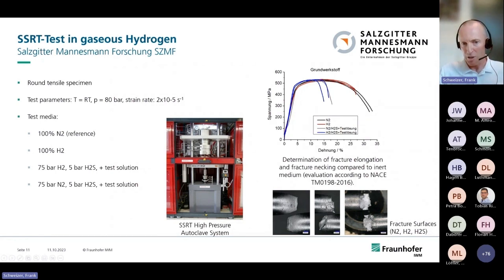So you have a tensile machine, what you see here, and you have an autoclave system where you can have high pressures of hydrogen gas. You can also cool it or heat it up a bit. And what you have to do, you have to measure these samples at a very low strain rate, so that the hydrogen has enough time to diffuse to the crack tip, as I showed in the first picture. So the hydrogen diffuses to the crack tip. You have to do all experiments with hydrogen at a lower rate than in standard cases.